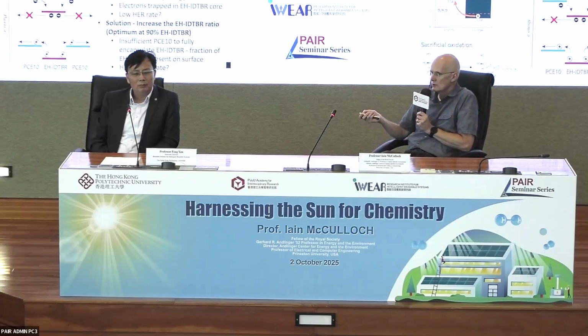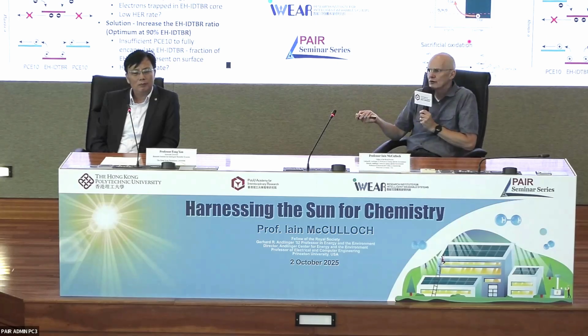Is it possible to use your new catalyst to split water, overall water splitting? So we can do this now. We haven't published this, but we are able to. Oxygen evolution is actually quite tricky. If you look at the papers that have shown it, after the talk, I'll show you our data. So we have this now.